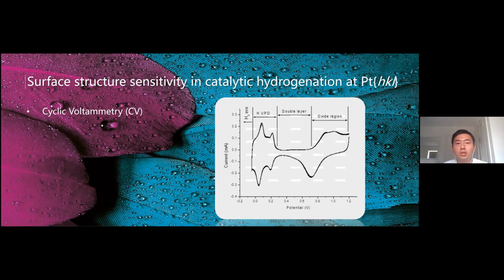Even on polycrystalline platinum nanoparticles, there are still many ordered facets on the surface. Different surfaces have unique cyclic voltammograms that we use to identify them, which is very important for selective hydrogenation on different platinum single crystal surfaces.